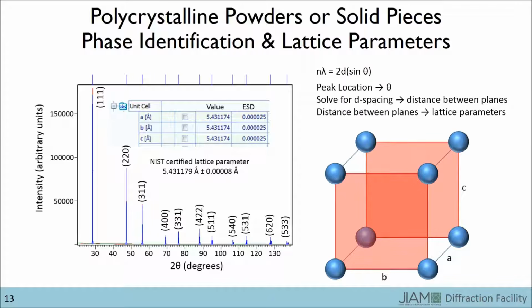In the simple cubic example from earlier, the d-spacing of the 100 plane gives all three lattice parameters a, b, and c. For the example shown on the left of the screen, it took less than 2 minutes to load the data into the analysis software and obtain the lattice parameters with incredible accuracy. Granted, this is an ideal reference material, so your experience may not be as fast, but the process is quite straightforward. If your material is a solid solution, utilizing Vegard's law along with the lattice parameters of the pure constituents and your sample could help you determine the composition of your sample.